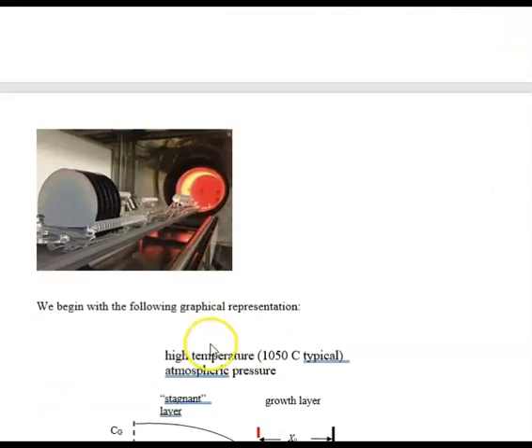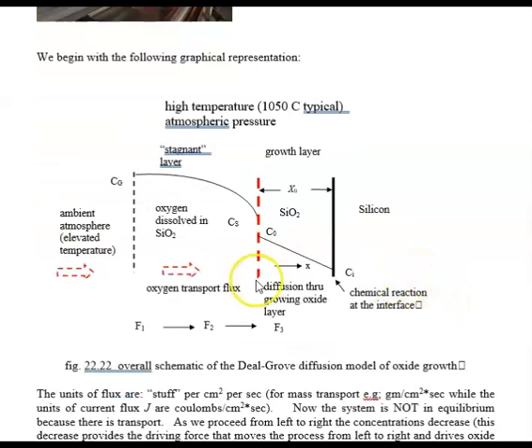So this is a picture of a furnace. These are the wafers which are being loaded into the furnace. This is the furnace. The growth process takes place at about on the order of 1,000 degrees centigrade, and it's typically done at atmospheric pressure. So this is the cartoon of what we'll be looking at, which describes the Deal-Grove model. And we have essentially 4 basic parts to it.